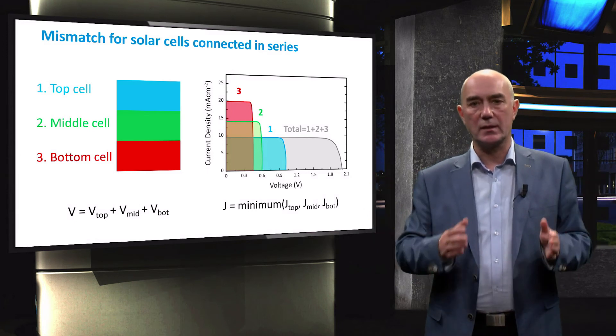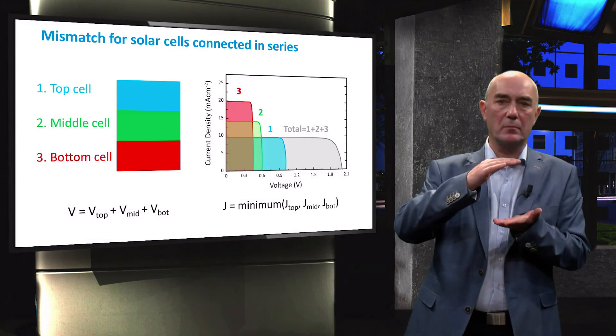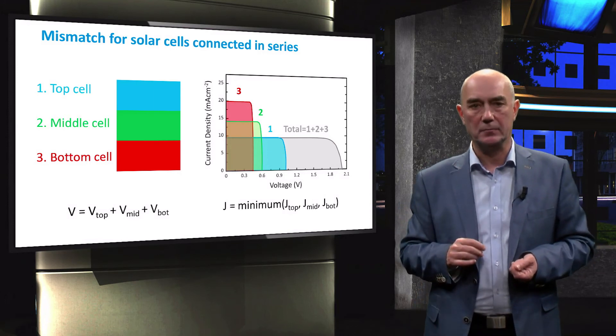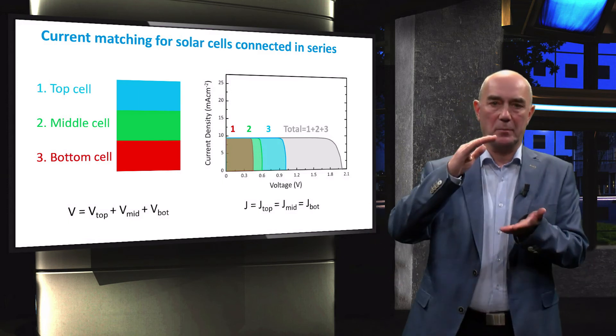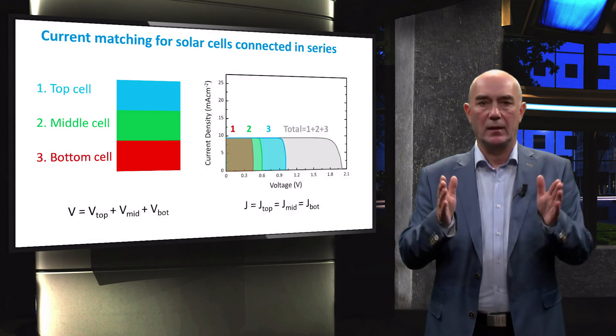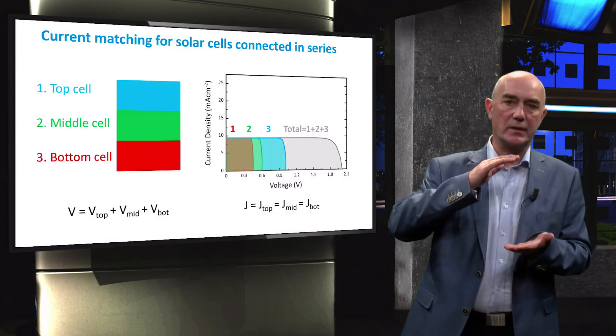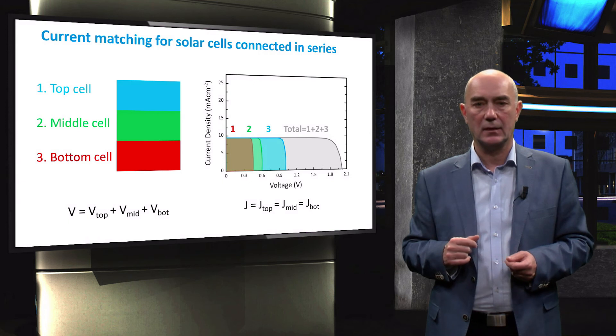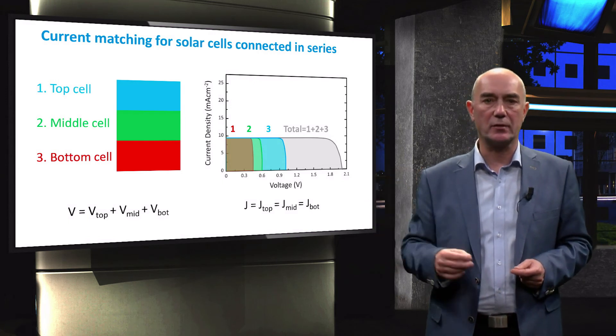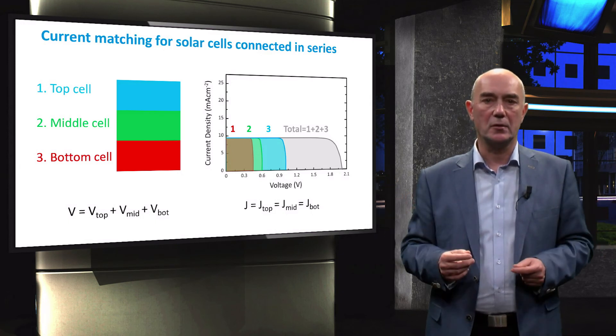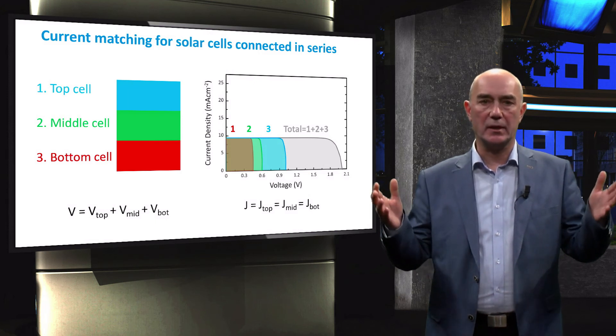The resulting open circuit voltage is the sum of open circuit voltages of individual cells, while the short circuit current density is limited by the lowest current density delivered by the top cell. To achieve current matching between the individual cells in a triple junction solar cell, the absorber thickness of each component cell must be optimized. We see from the JV curve diagram that in the optimal situation, the maximum power point of each component cell delivers the same current density. You can calculate the optimum absorber thicknesses for current matching if you know the refractive index and the absorption coefficient of all the materials in the solar cell. For this, you will need the Fresnel equations and an understanding of how light is absorbed in a solar cell — concepts you learned earlier in this course.